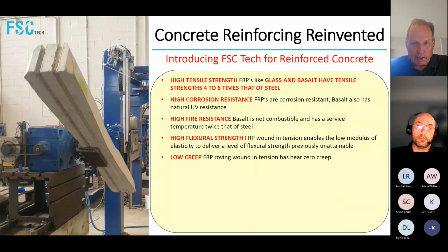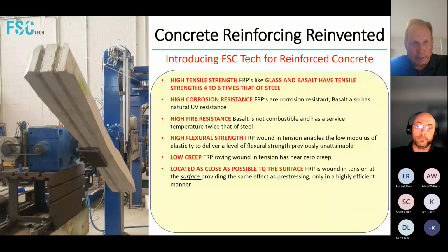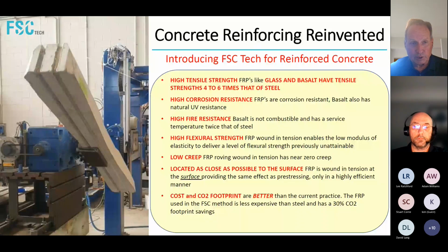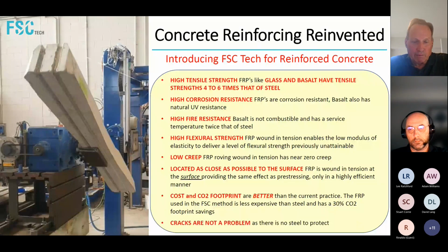Once you wind this in tension, your material has near zero long-term creep. And of course, it's located as close to the surface as possible because it is at the surface. So again, we're providing the same effect as pre-stressing, providing a post-compression to the tie in this case, but it's being done in a very highly efficient procedure. And the cost and the CO2 footprint are both better than what's being done today. If you take how much the roving material costs for a tie compared to what the steel costs per tie, it's less. And it has a 30% CO2 footprint savings to go with it.